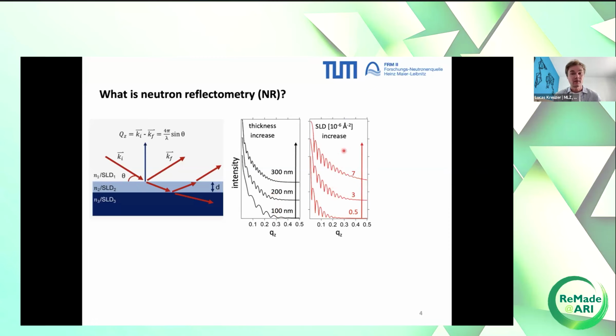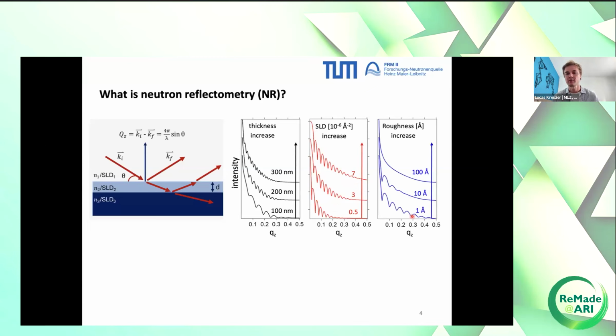Another piece of information we extract is the SLD. SLD stands for scattering length density. It's a measure of how strongly your film interacts with the incoming neutrons. An increase in SLD leads in particular to an increase of this total reflection. So this critical edge here, once the neutrons are able to penetrate the film, is shifted to higher QZ values, while also these fringes are more pronounced even at the high QZ range. And a third piece of information we extract would be the roughness. So the rougher the film, the stronger the dampening of these fringes. And this is also one of the prerequisites of these films. If you want to do neutron reflectometry, they have to be reasonably smooth in order to get reflectivity curves that you still can analyze.